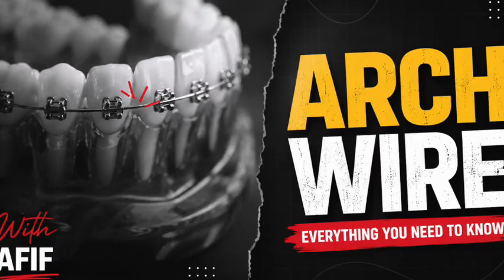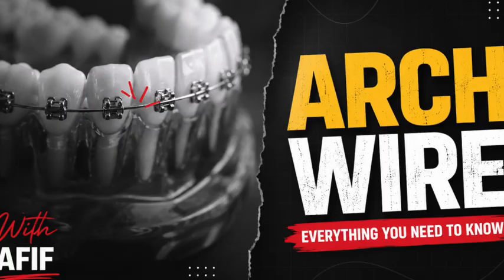Let's break down that specific recipe, 18/8 stainless steel. Sure. What do those numbers actually represent, and why does that specific blend survive the mouth so well? So the numbers are the exact metallurgical composition. It's 18% chromium and 8% nickel, added to the iron and carbon base. 18% chromium, 8% nickel. Okay. The chromium is the absolute magic ingredient for corrosion resistance. What does the chromium do? When chromium is exposed to oxygen, it reacts instantly to create a microscopic passive oxidation layer on the surface of the wire. Like a shield. Exactly like an invisible self-healing shield. It completely isolates the underlying iron from the moisture and acids in the mouth, preventing rust entirely.